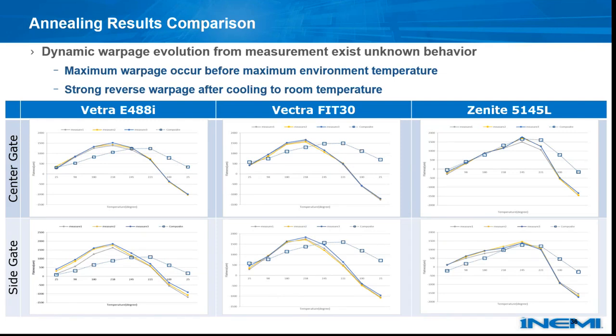However, even though we found a reliable mesh for validation with the mesh convergence test, when we compare with the experimental result, the experimental results show some characteristics that are difficult to explain. On this page, we can see the dynamic warpage of the two gate designs and the three material grades. The solid curves indicate the experimental data from 3 different samples, and the dark line and the hollow squares represent the simulation result. The simulation results show flatness proportional to the temperature, and the flatness changes when cooled down to room temperature due to the stress release.